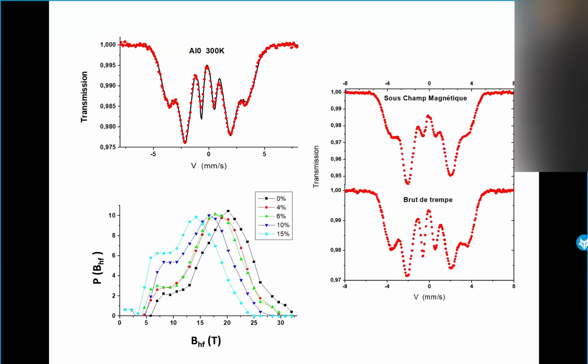And I remember it was during my first thesis, and of course, I checked the amplitude of the hyperfine field distribution, the influence of the quadrupolar shift, the influence of the isomer shift, or the intensities of the second line. And finally, we concluded that, of course, it's possible to get a free texture spectrum by rotating the sample with the magic angle. Because during the quenching, finally, you will get some orientation of magnetic domains. It's according to the cooling of the system.